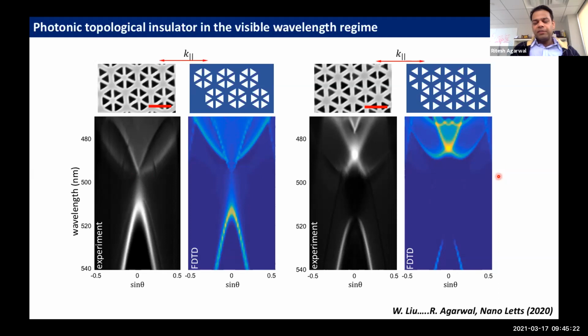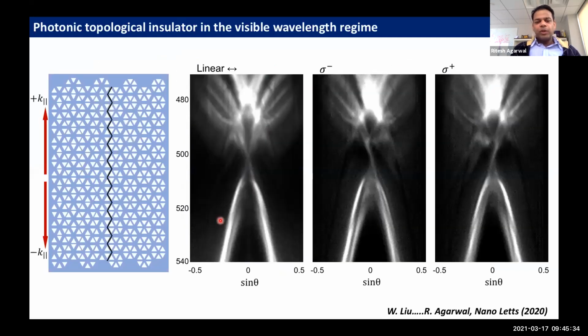And in the inverted regime, you can see it's reversed. So this is the d orbital. That's why it's dark at this gamma point. And here it is bright. So it's an inverted structure. And when we create an interface between these two photonic structures, there's a mode here, and photons can only propagate along this zigzag mode. So if you do k-space spectroscopy at the interface, we see both the spin-dependent modes.